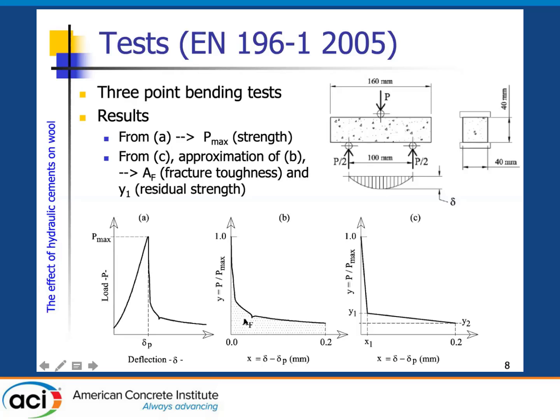In this way, we have the area defined by this diagram, which is a kind of fracture toughness of the material we are going to use. If you want, this post-peak behavior can be simplified by a bilinear relationship like this one. And from this bilinear relationship, we can compute not only the AF, the fracture toughness, but also Y1, which is the post-peak residual strength after the growth of the crack.